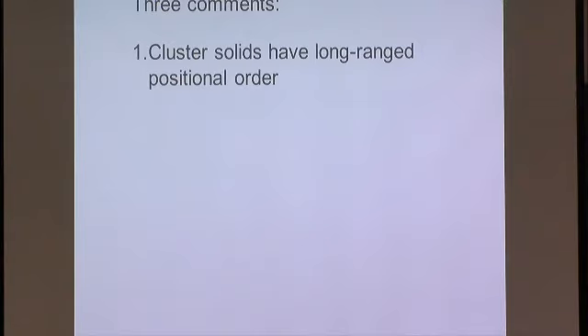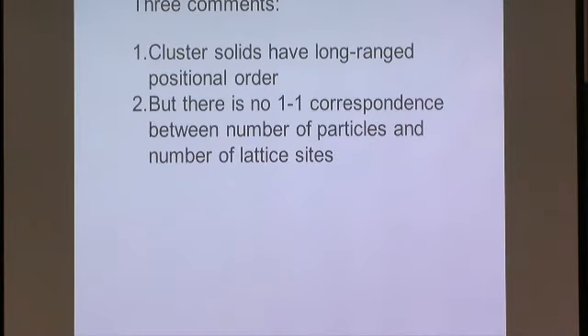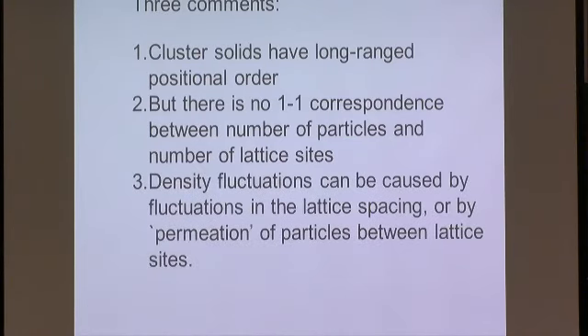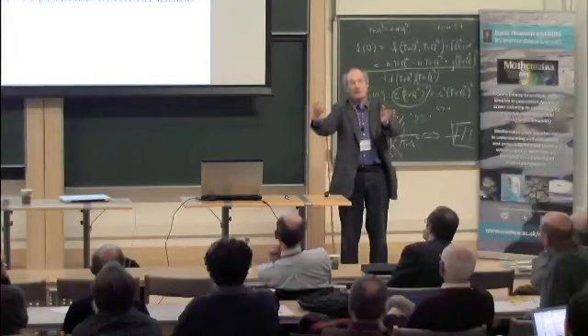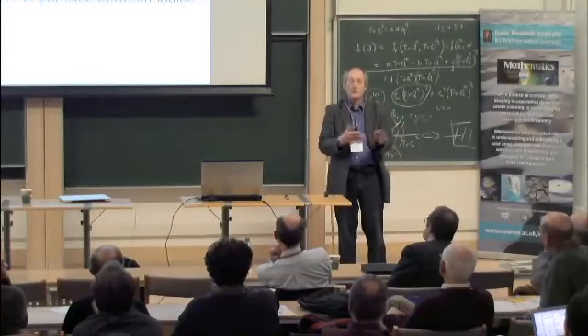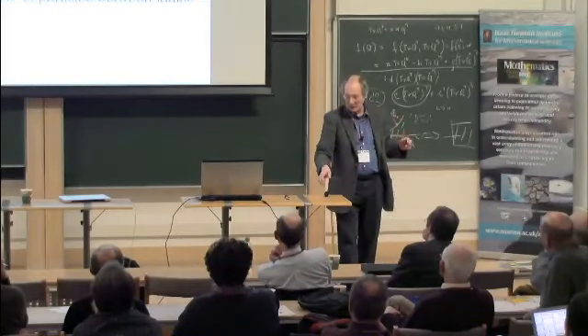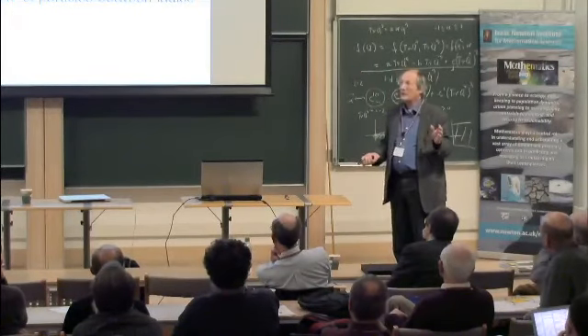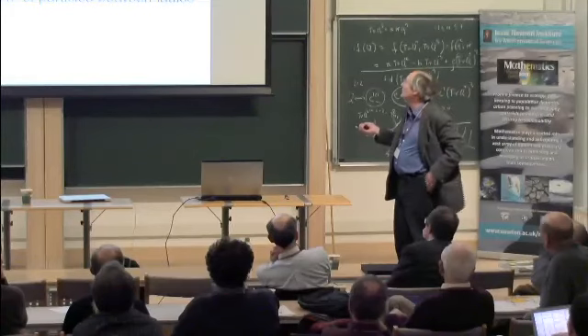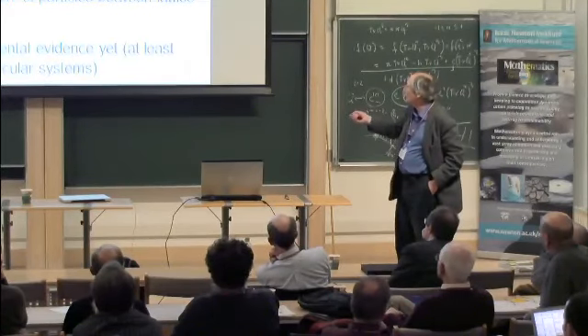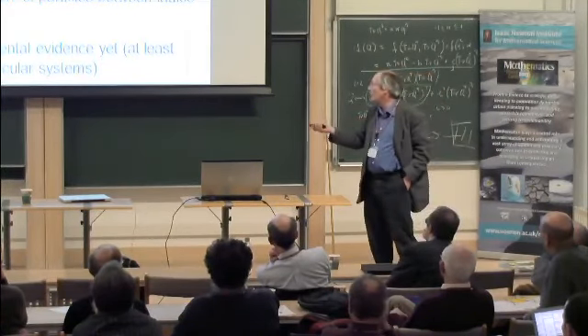So cluster solids, they're real crystals. They have long-range translational order. There's no one-to-one correspondence between the number of lattice sites and the number of particles. Density fluctuation, it's a bit like the smectic. You have two ways you can do density fluctuations. You can vary the density by changing the lattice spacing, or you can vary the density by having particles permeate from one cell to the next. So if you wish, you have two sound modes. That's an interesting thing, that if only these things had ever been made, it could be measured experimentally, but until now there's no evidence, at least no evidence for molecular systems.